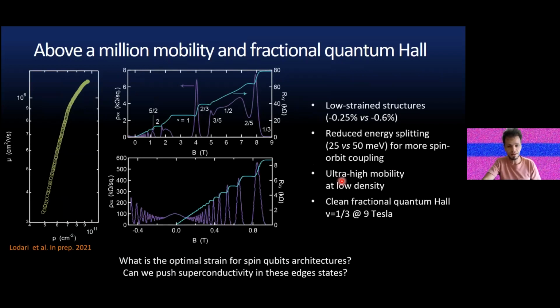The last few things I want to say about germanium is that this might be the third iteration that we'll go through. So we haven't touched the strain so far for devices. But again, at the material level, we tend to advance faster, and then eventually this will go into devices. Here I want to show you a recent result from Mario that we are writing up as well: by tuning the strain, so doing a bit less strained structure, we really have a super high quality hole gas with reproducibility. We achieve mobilities well in excess of a million, and also low percolation densities in this case. So in a way, we get both on the same wafer.